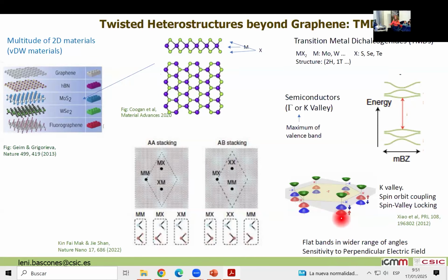And this is one thing that I was going to mention later. I think nobody is questioning that. I don't know if this is the splitting that you referred to. In each of the valleys you have one spin, in the other valley you have another spin. To have at the Fermi level two spin channels degenerate, sorry, these are not degenerate, these are split. This is specific to the chalcogenides, but the point is that they are splitting already in k space, in the sense that in the monolayer, in one of the valleys you have one spin, and in the other valley you have spin down.